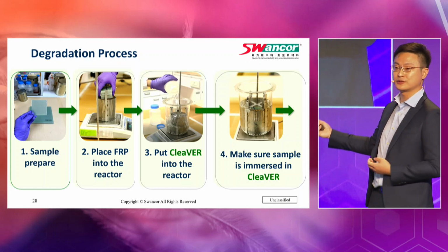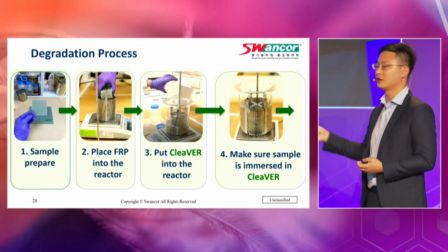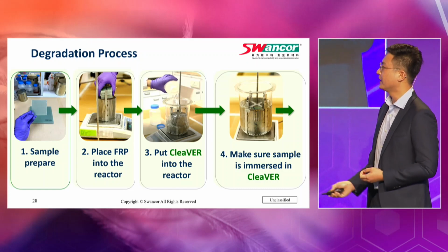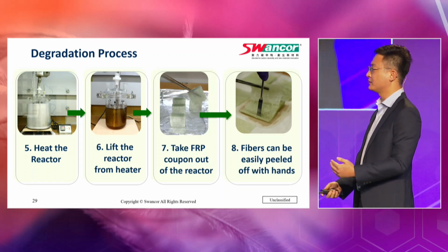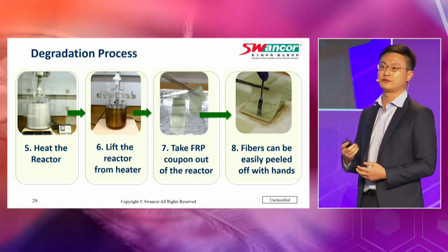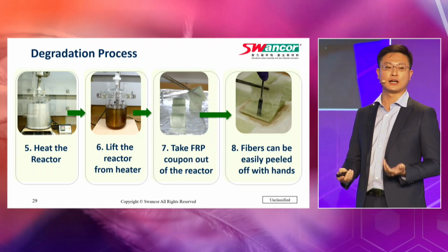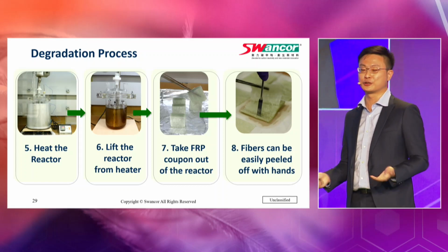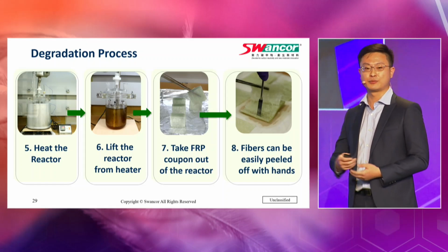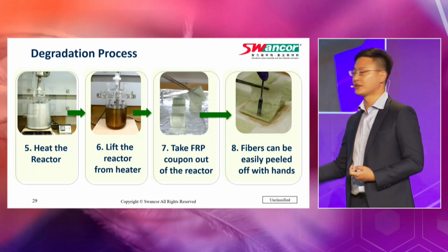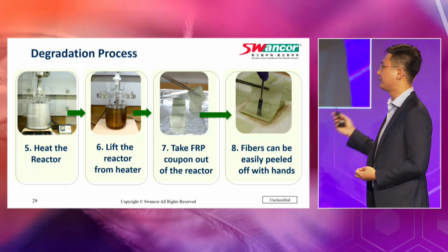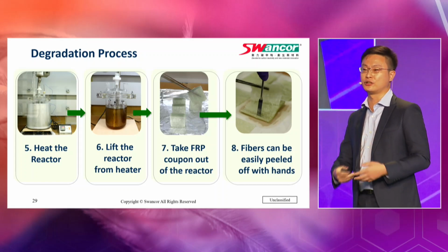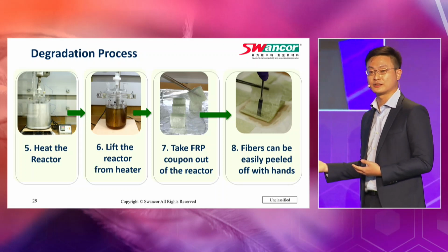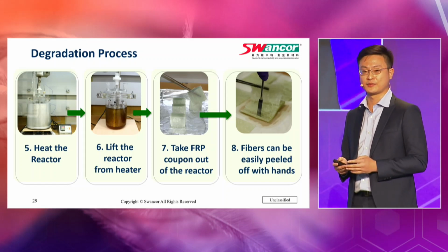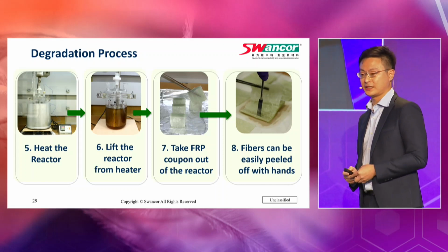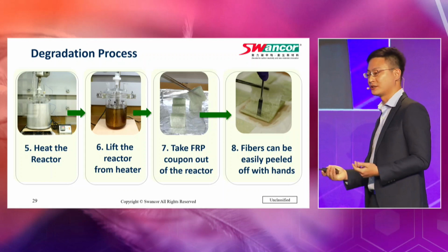After that, you just pour the CleaVER into the reactor and make sure all of the parts are immersed in it. Then you just need to heat up the reactor with agitation to, for example, 130 degrees for 2 to 3 hours. After that, the reaction is just finished. You don't need to do any other process. Then you can easily separate the fiber from the degraded oligomer. And you can see that the fiber can be easily peeled off by hand. Since we don't apply high temperature, high pressure or strong acid solvent in the recycling process, the fiber can keep its mechanical properties after the degradation process. So let's take a look at a video, and you can see how easy this process can be.